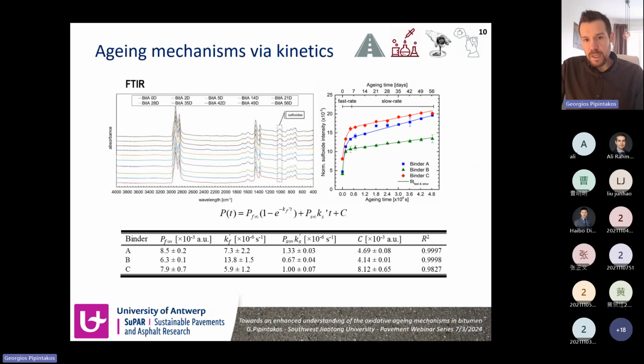It should be noted also that sulfoxides were more prone to be produced at this rather low temperature of 50 degrees at which the modified thin film oven testing was conducted. And this is in line with literature that mentions that carbonyls are probably more prone to be produced when higher temperatures are used. The idea of using 50 degrees, of course, was that we tried to simulate as close as possible, but also as fast as possible.